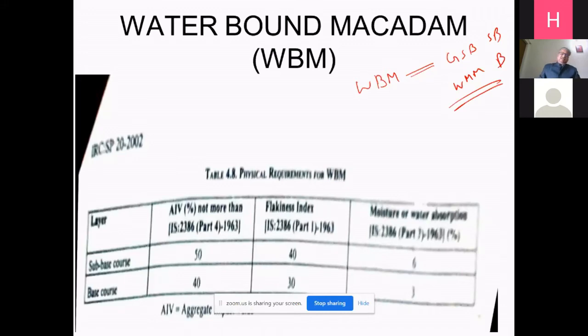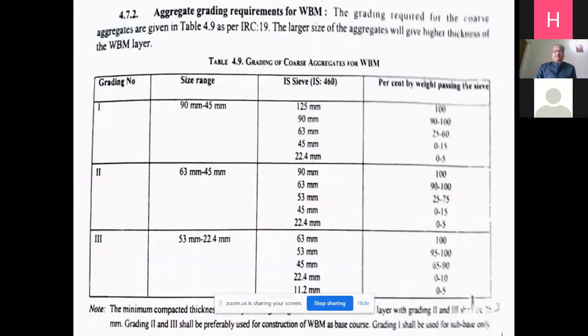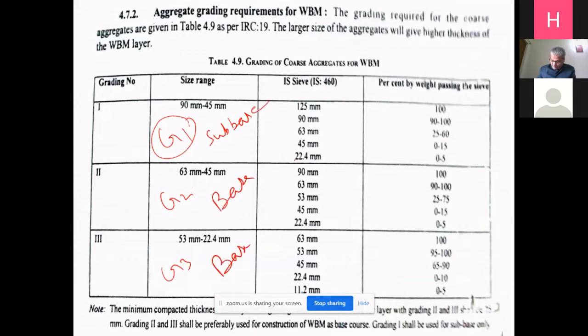But I can bet with anybody that if you make the WBM as per rule only, then nobody can put more soil there. WBM has 3 grades: G1, G2, G3, with sizes 90 to 45, 63 to 45, and 53 to 22.4. G1 is used for sub base. This is used for base. This is also used for base. Its thickness is 100 mm. It's 75 mm. It's also 75 mm. So you have to use these materials, and its CBR is 100%. It is assumed.